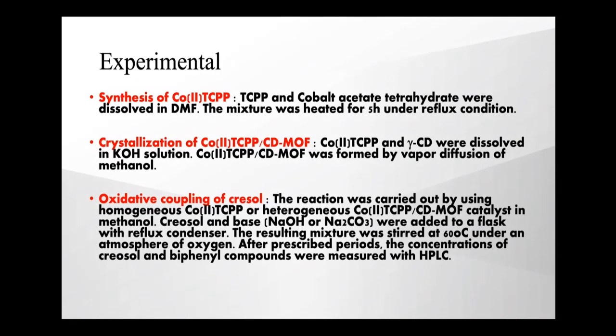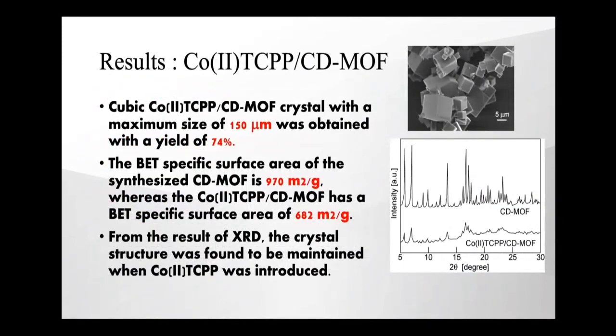Creosol and base, sodium hydroxide or sodium carbonate, were added to a flask with a reflux condenser. The resulting mixture was stirred at 60 degrees C in oxygen. After a prescribed period, the concentrations of creosol and biphenyl compounds were measured with HPLC.